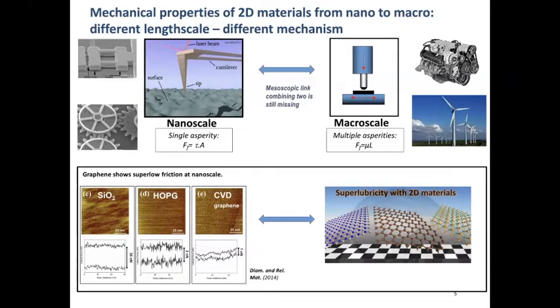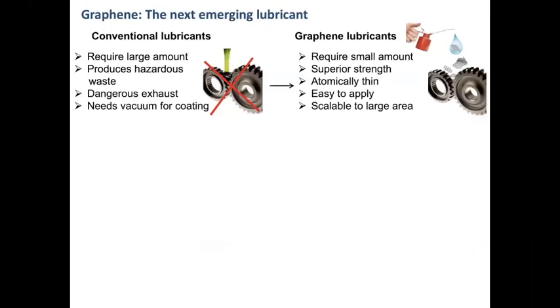Transitioning from this nanoscale up to the macroscale, that's where we see lots of challenges, because it's not a single asperity anymore. So we need to worry about this whole system, about the roughness profile, about what is happening on the surface and how it's changing, because all of us know that with sliding, with tribology, we have modifications of the surfaces. How these modifications of the surfaces affect the overall behavior, that's where we see lots of the complications coming. So our goal in all of these studies specifically was to understand how we can transition mesoscopically, linking these two different states: one of understanding what is happening at the nanoscale at a single asperity, and then going to the macroscale to use this knowledge from the nanoscale and build up on it to get this superlubricity state of zero friction regime.